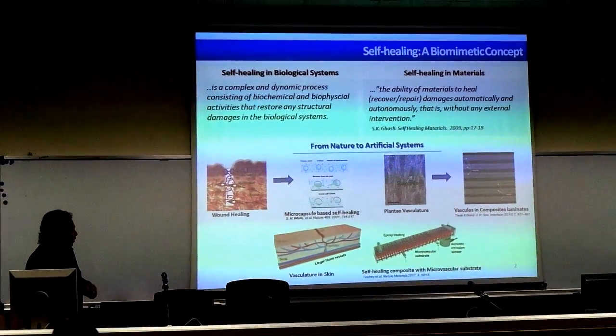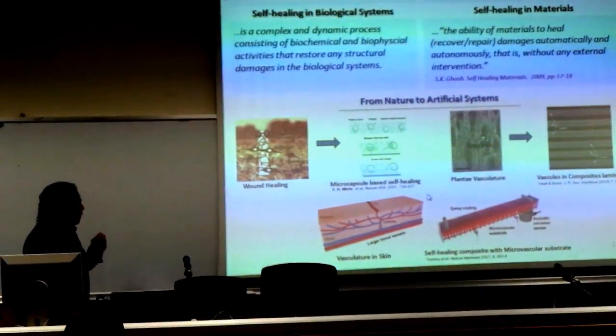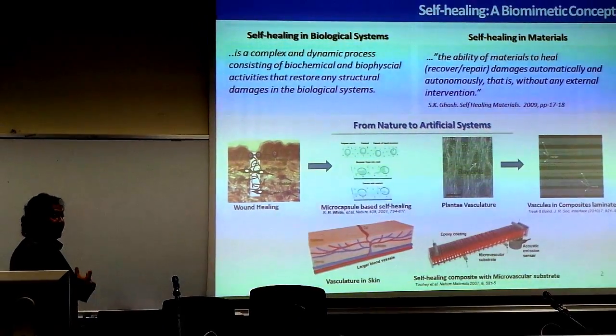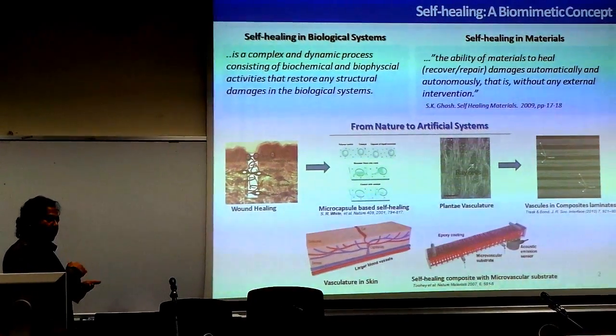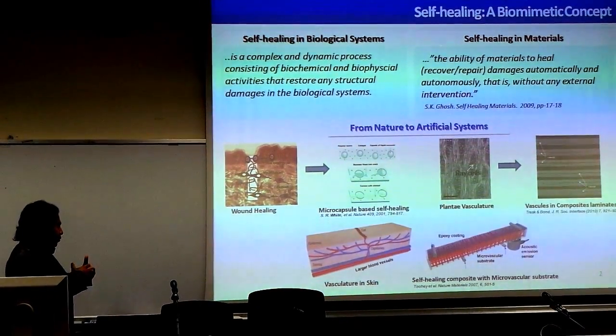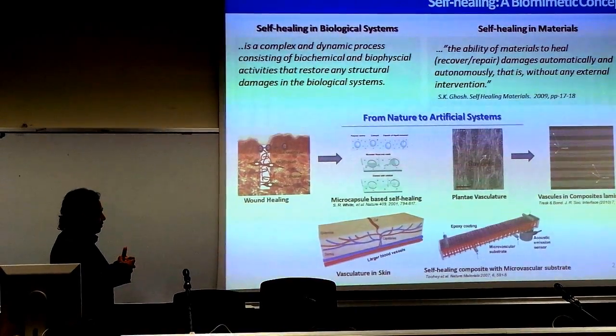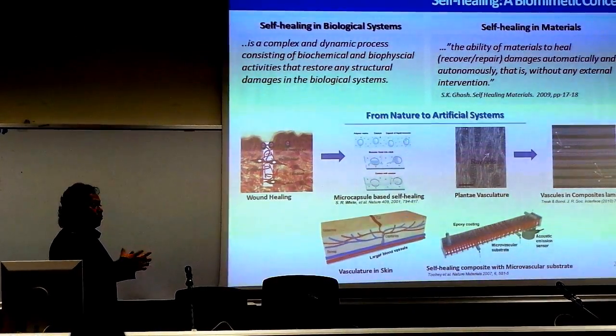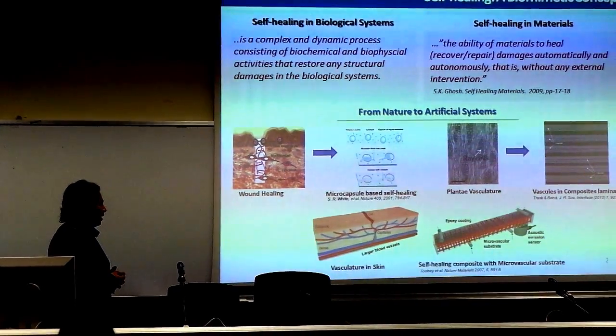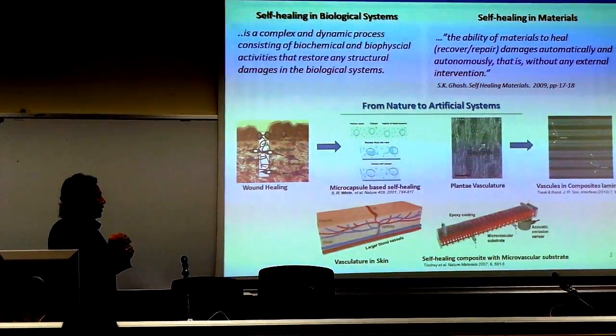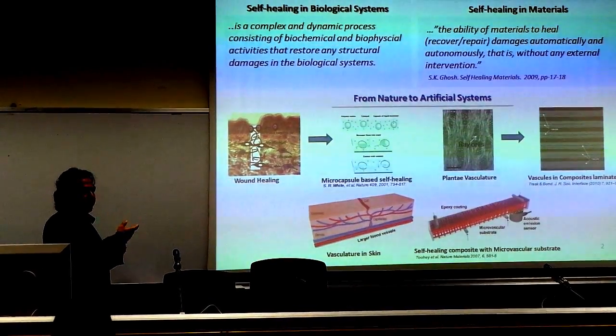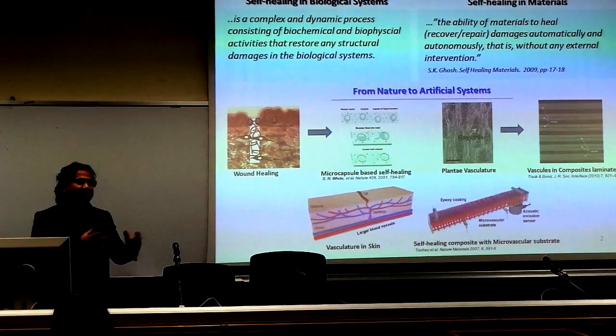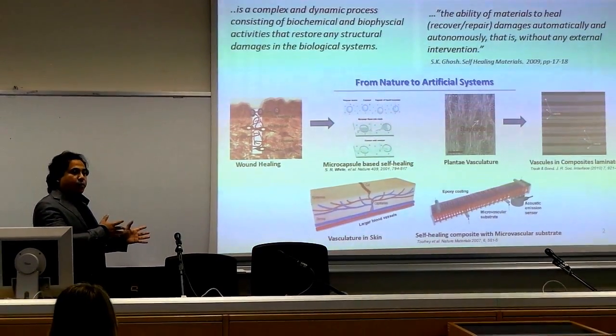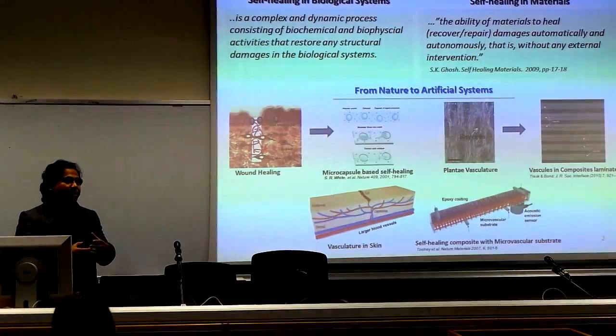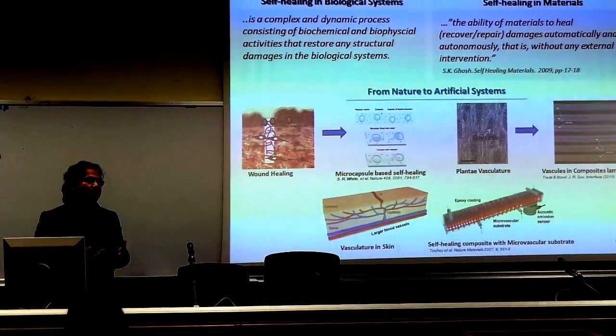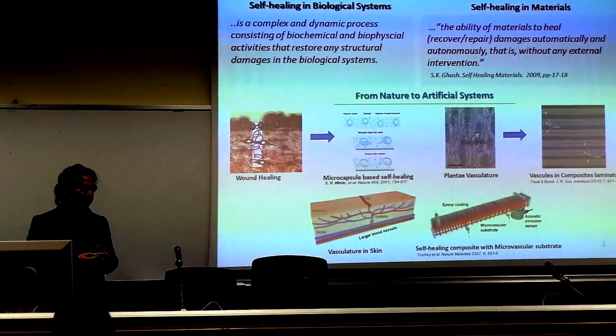Another interesting approach was developed by Professor Toohey et al., and they tried to mimic the vasculature in skin, which is the blood vessels under the lower epidermis of our skin. They tried to mimic this network of blood vessels inside a composite by embedding a three-dimensional network of hollow glass fiber in the composite. Upon crack initiation, due to the internal pressure difference, the healing agents will go to the crack and heal the crack. These are very promising extrinsic types of self-healing materials. However, because of their very expensive synthetic route, they are still not very technologically convenient.